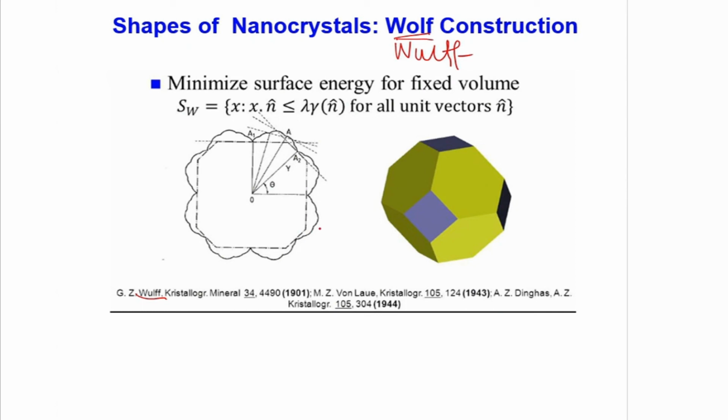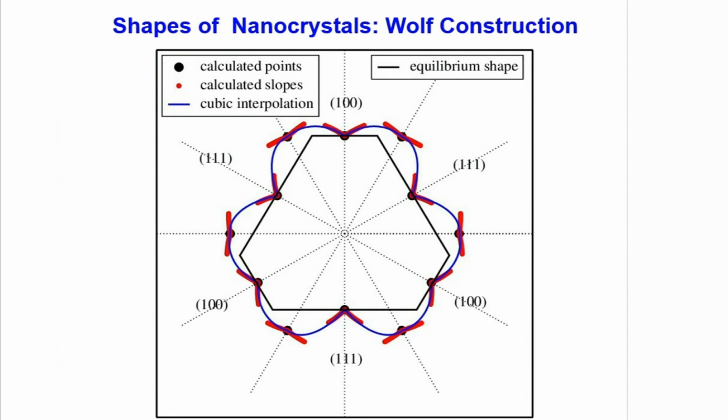Even if you have arbitrary surface energy, you can draw these normals and do this. I'm doing it again. This is a cuboctahedral shape. So this is the reason why FCC crystals or FCC structures show such cuboctahedral shapes. Again, I'm showing you some arbitrary shapes. You can see here, it's a very peculiar shape actually, okay. Here you have 1-1-0 facets and 1-1-1 facets, right. So this is the surface energy envelope. And each one is shown by such nice points. You see here, these points are shown. So you can generate the shapes, right, if you know this. It is not difficult at all for you now.